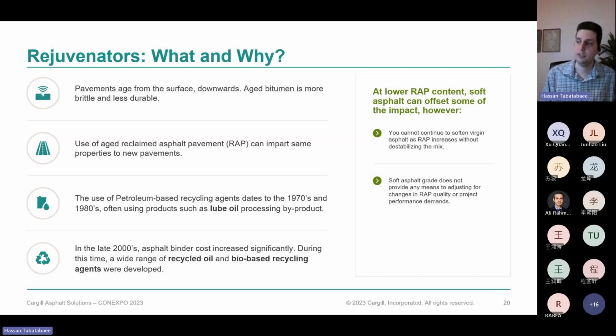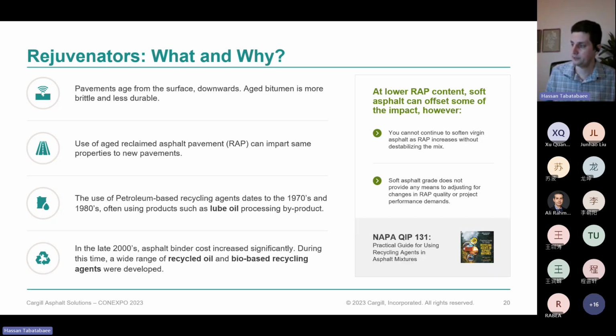However, I would say in the late 2000s, recycling oil had another resurgence with the price increase of asphalt at that point. However, we started to see a lot more bio-based recycling agents coming into the market. Recycling agents have advantages for use in recycling over using a soft bitumen. Part of it is because there's only a certain amount of bitumen softening you can do before you destabilize the mix, and it becomes a lot harder to balance the rutting and cracking performance at higher RAP contents when doing this.